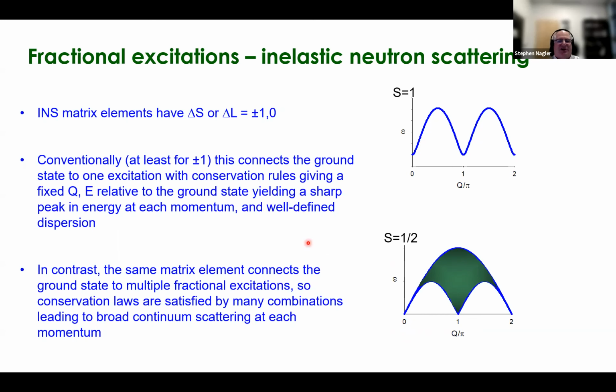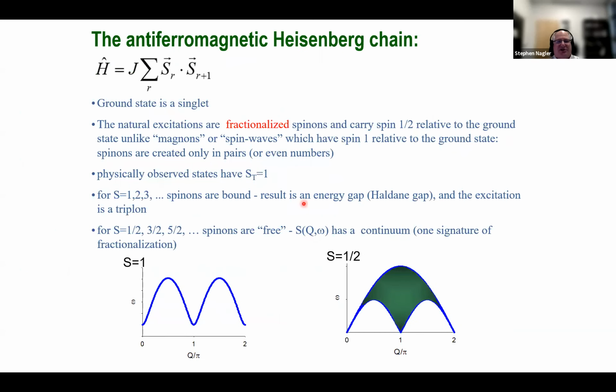The examples that I've plotted here happen to be germane for the antiferromagnetic Heisenberg chain, for which it's known that the ground state is a singlet. It turns out that the natural excitations are spinons that have a spin of 1/2 relative to the ground state, unlike regular magnons or spin waves, which have a spin of 1 relative to the ground state. And the spinons in the neutron scattering experiment are created only in pairs or even numbers. So the physically observed states have a total spin of 1.